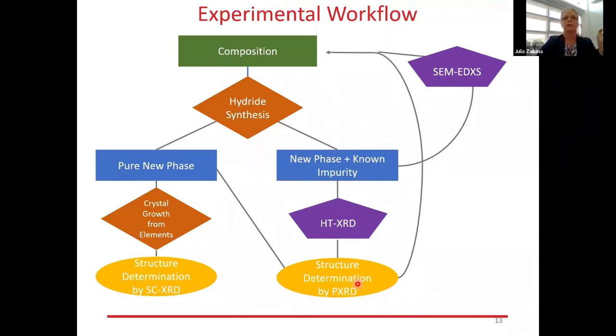In some cases where crystals for single crystal X-ray diffraction are not available, we can determine the structure from powder X-ray diffraction. And we also use other methods to determine the compositions of our phases, for instance SEM-EDX, to determine the composition of the phase. Then once we have a better understanding, we decide what our next composition to target is.